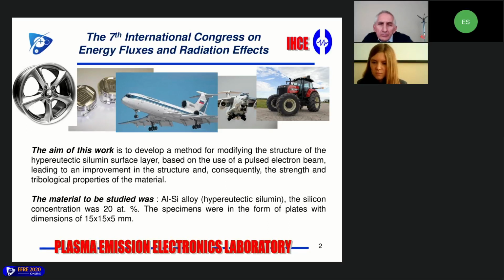And chemical modification, for example, we can use strontium to improve mechanical properties of eutectic silicon, and we can use phosphorus for hypereutectic silicon. And this treatment may modify the coarse plate-like morphology of silicon particles to fine fibrous. And there are no elements known that beneficially modify both the eutectic and hypereutectic phases.